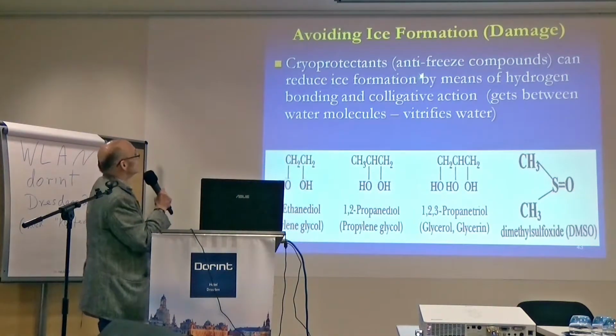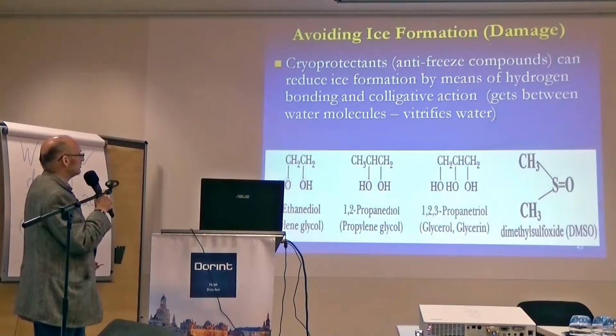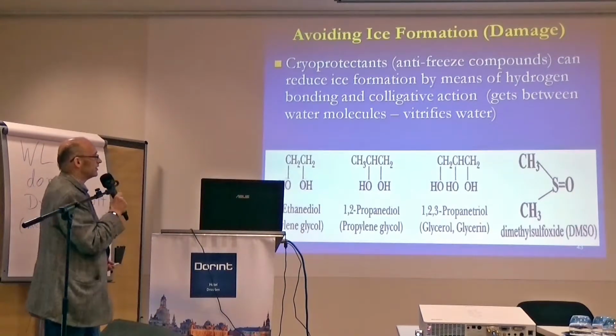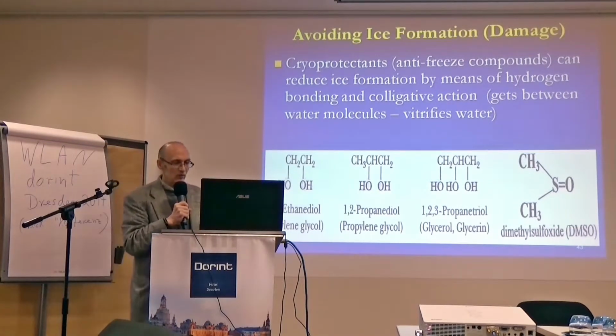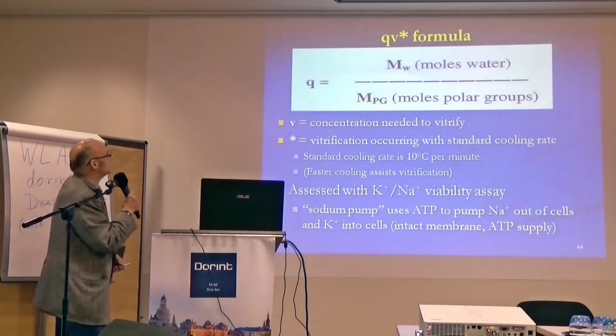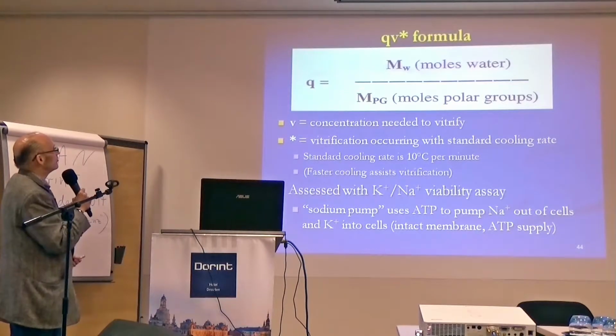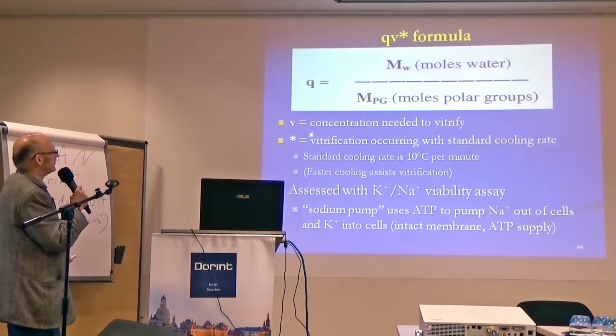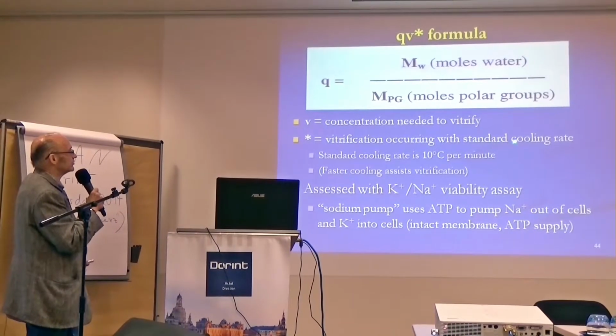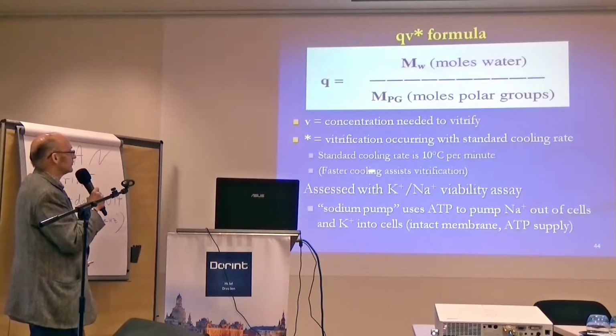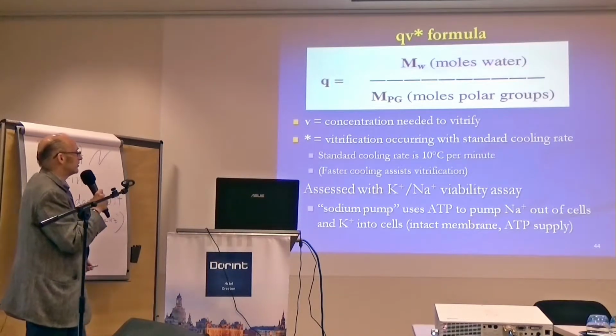As I mentioned, the mechanism of the cryoprotectants seems to be based on hydrogen bonding groups that interfere with the hydrogen bonding between water molecules that results in ice formation. So there's the formula. The Q part of QV star refers to moles of water divided by moles of polar groups in the cryoprotectants. V is the concentration needed to vitrify, and the star part refers to vitrification occurring under a standard cooling rate. So faster cooling assists vitrification. The standard cooling rate is 10 degrees Celsius per minute.